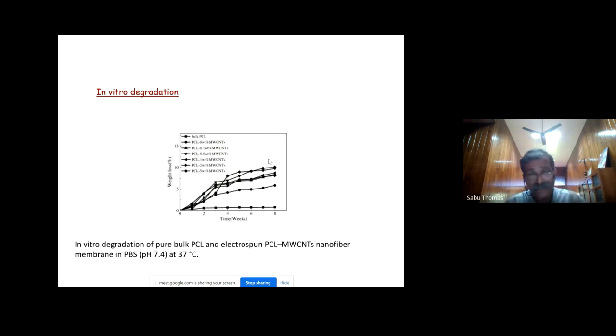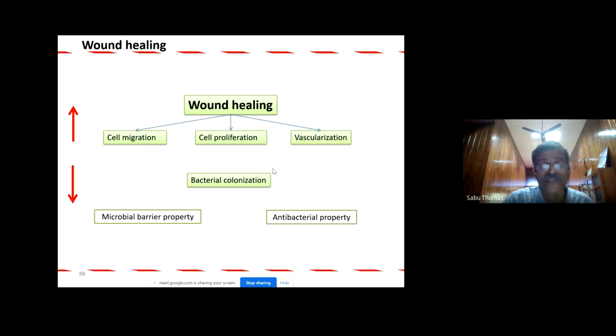In vitro degradation. You see, when you put a scaffold in your body, after the tissue regeneration, the scaffolds have to disintegrate. Scaffolds have to degrade. Scaffolds have to disappear. So nanoparticles have a very important effect. Look at this, the pure PCL scaffold, as a function of time, after 8 weeks, the disappearance is very low. But if you put carbon nanotube, you see the scaffold disappears much faster. Therefore, introduction of nanostructures will help the degradation of the scaffolding material. The in vitro degradation of the scaffold could be faster.